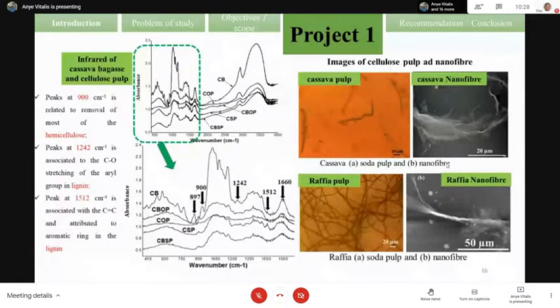there is a removal of the amorphous peak, like the peak of 900 which corresponds to hemicellulose, and the peaks of 1,242 and 1,512 which correspond to lignin. Also, in the figure on the right, you can see that from the pulp to the nanofiber, there is a significant reduction of the size, which shows the efficiency of the process.